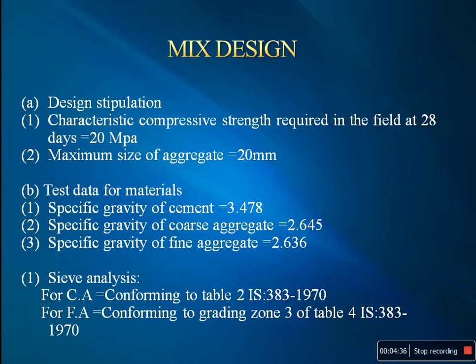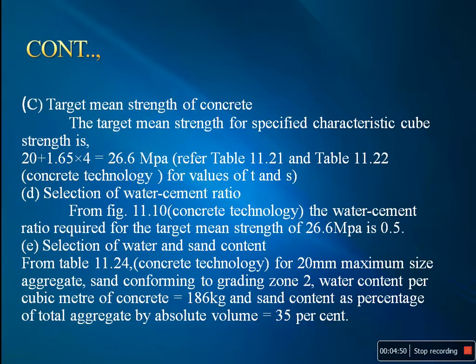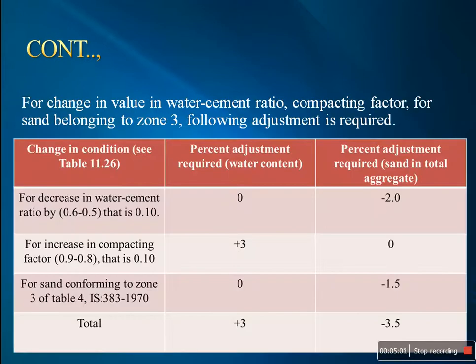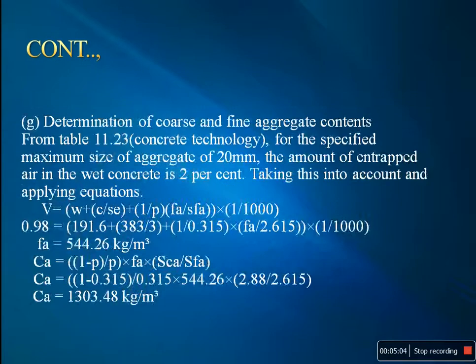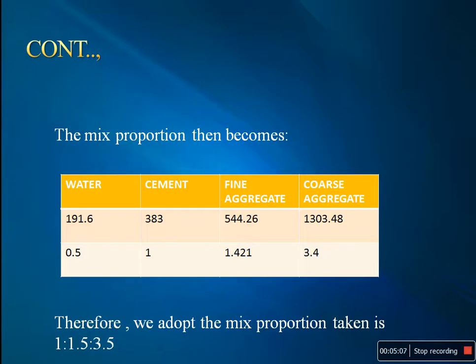My mix design: the maximum size of coarse aggregate is 20 mm. The test data for materials: the specific gravity of cement is 3.478, the specific gravity of coarse aggregate is 2.645. And the target mean strength for the specific characteristic cube is 26.6 MPa, and the water cement ratio is 0.5. From the result I have obtained the mixture proportion: water is 0.5, cement is 1, fine aggregate is 1.41, and coarse aggregate is 3.5.